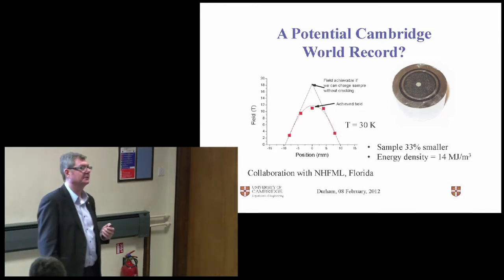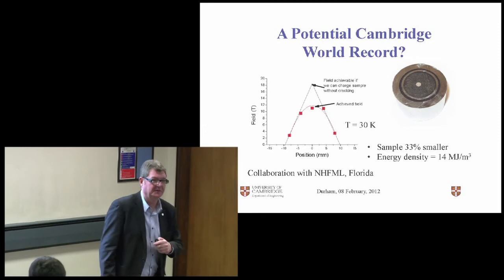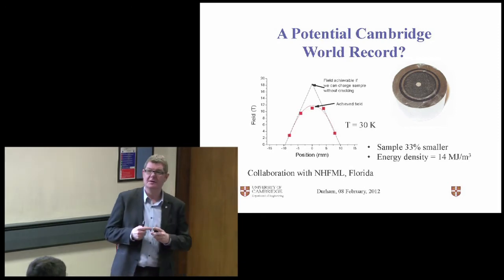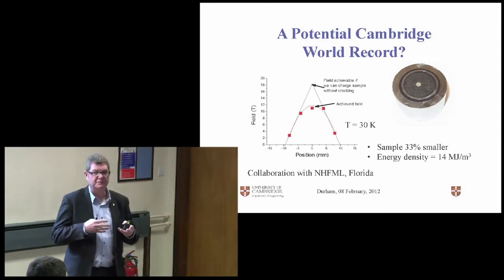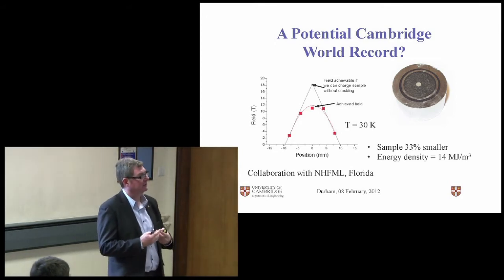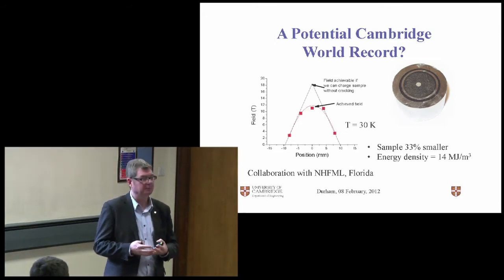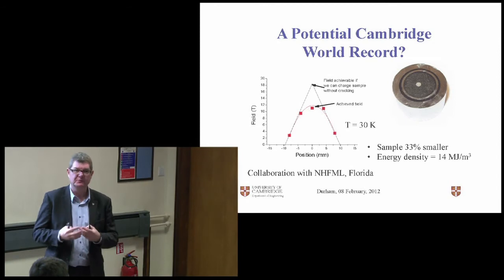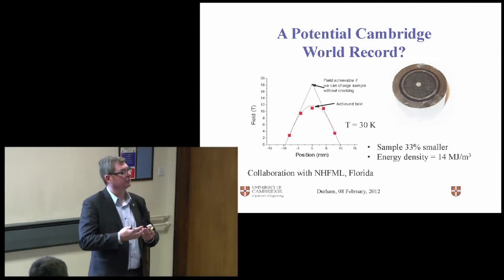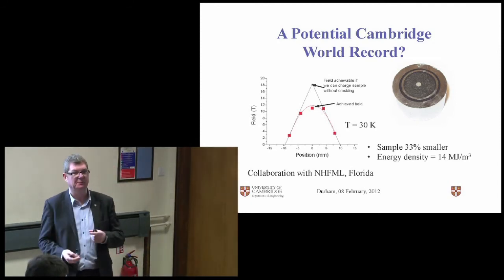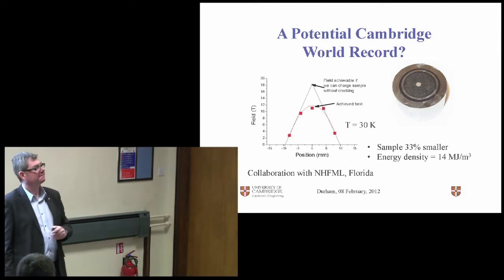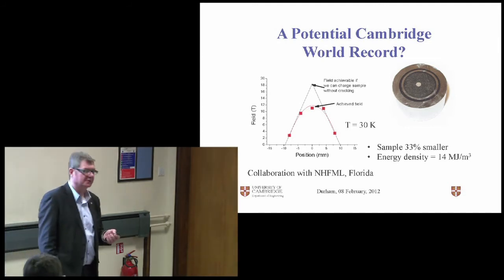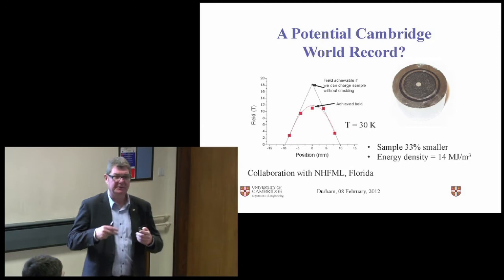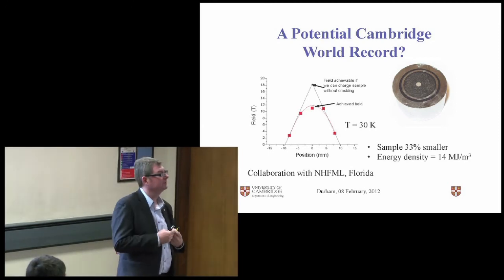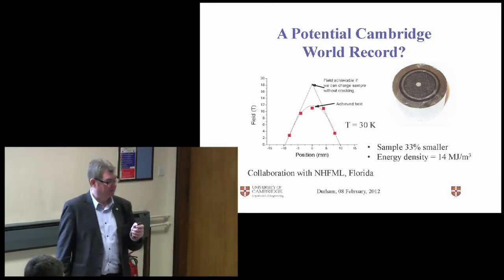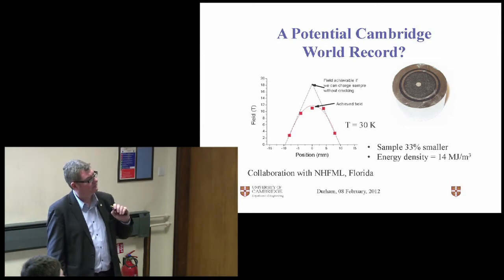So the first attempt, we trapped 3 Tesla. We trapped only 3 Tesla because there were lots of flux jumps at very high field, and that gives you lots of heat. That means that bits of your sample go normal, so a current has to go round, there are big forces, and therefore you can destroy your sample, which we did very effectively. But then we designed a way of eliminating that heat leak by putting a high conductivity material through the centre of our sample. And we went back just before Christmas and repeated it.